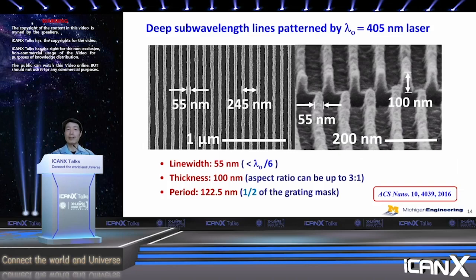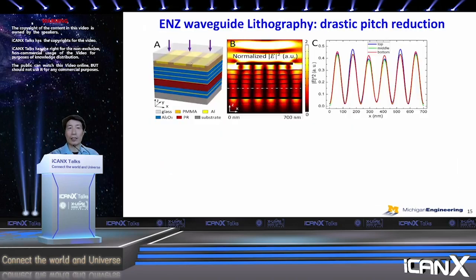So this is the second work that we came up with. It's using a multi-layer structure. ENZ stands for epsilon near zero. It's a metal-dielectric multi-layer, and you can tell this multi-layer is anisotropic. In fact, the effective permittivity along the horizontal and vertical directions are different. One can even be negative. And we want the horizontal component to be close to zero. That's where epsilon near zero comes from. And this gives rise to a desirable wave. So we treat this as a waveguide as well.